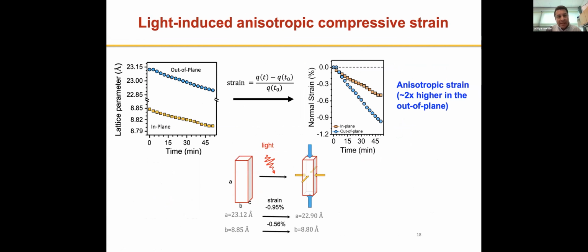So looking at this, the first thing we wanted to look at is the lattice parameter. And so we plotted the out-of-plane lattice parameter and the in-plane lattice parameter. This shows that over time, both of these are contracting. And then we can actually plot the normalized strain. What we found is that the lattice contraction is much stronger in the out-of-plane direction, about 2 times stronger than in the in-plane direction, which is shown here by the blue plot, whereas this yellow plot is showing you the one in the in-plane direction.